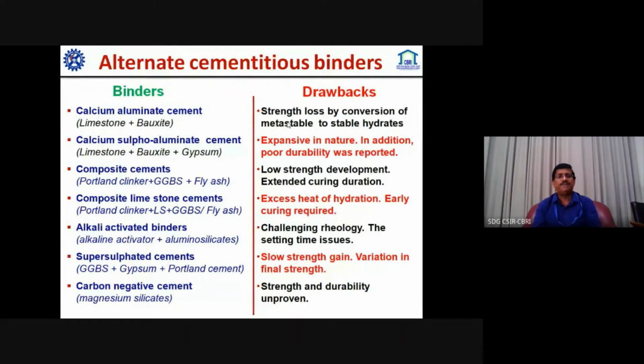Similarly, composite limestone cement, where the main thing is to avoid calcination or heating to make a clinker. So other types are made with crushed or ground limestone, GGBFS, fly ash, and other things. We utilize more ground limestone in the cementitious material.